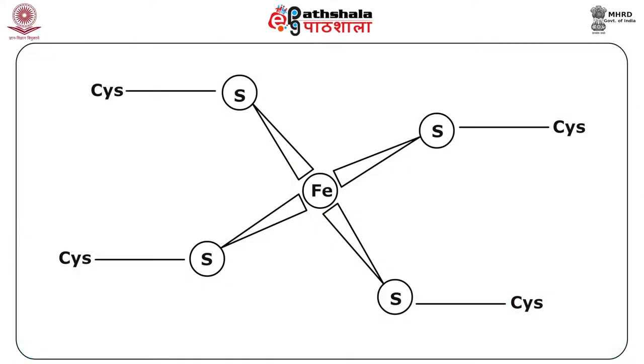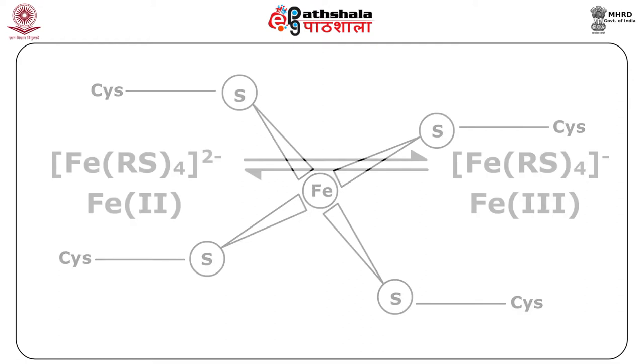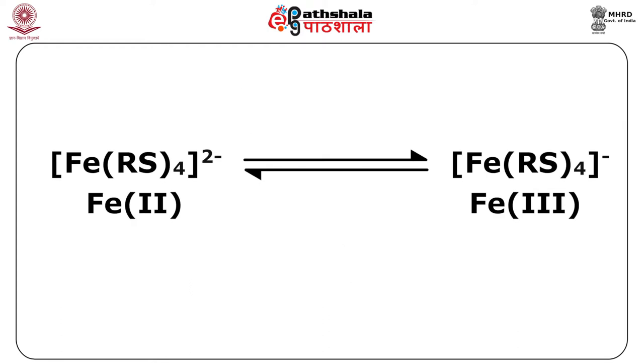This protein is of bacterial origin and was first isolated from Clostridium pasteurianum, but was later found in a number of anaerobic microorganisms. They comprise one iron atom, which is tetrahedrally coordinated to four sulfur atoms coming from the cysteine residues present in the protein chain of 55 amino acids. This has been represented in the figure. The redox center is composed of high spin iron 3 without inorganic acid labile sulfur in the core group. More than one iron center of this kind might be present in a molecule. The figure presents rubredoxin. The rubredoxin is a one electron transfer agent with Fe2+ and Fe3+ having high spin configuration.